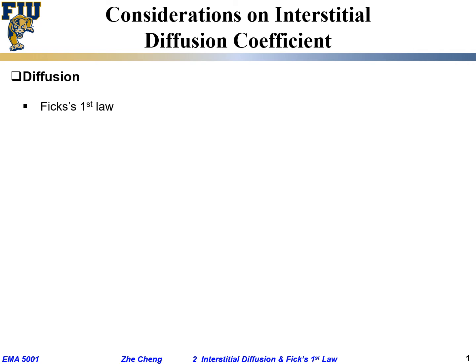Let's have some considerations. What did we say about Fick's first law? We said it relates flux J with diffusion coefficient and the concentration gradient. In one dimension we write it as J = -D ∂C/∂x, that's Fick's first law.